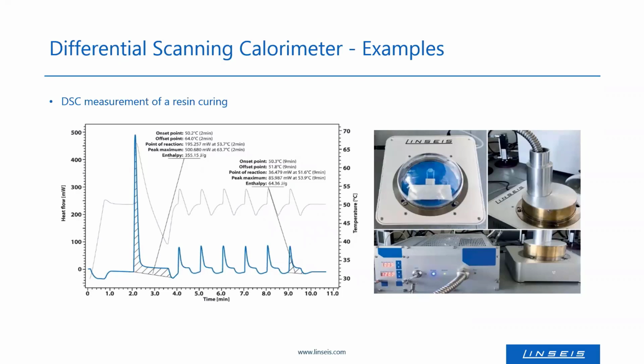And in the used materials, I mentioned those resins which need to be cured under UV light. For the Chip-DSC, we also offer an add-on with which one can cure the material. Here you see a measurement, in this case, of a mixture of resin that was placed in the Chip-DSC with this add-on, and by that it was irradiated with UV light pulses, and the measurement was repeated so many times until no change in the peak area was detected.